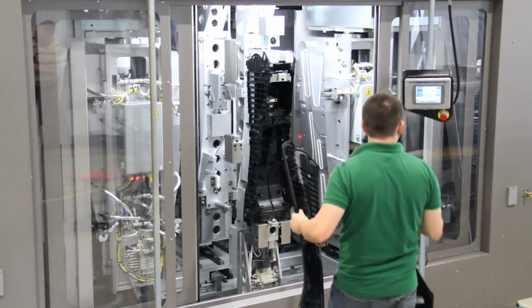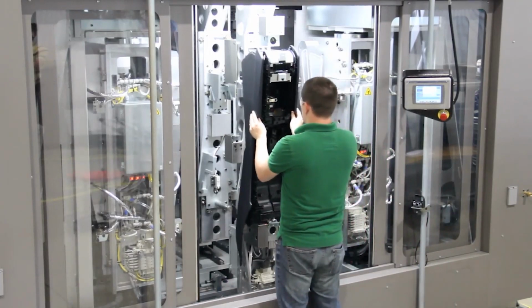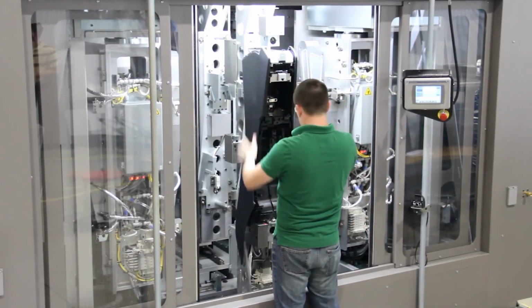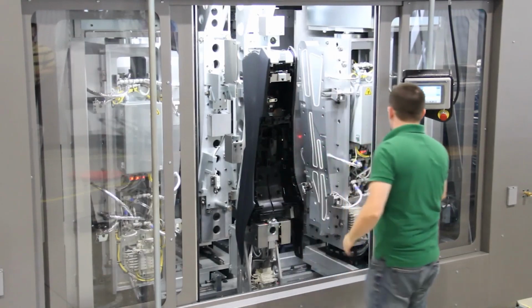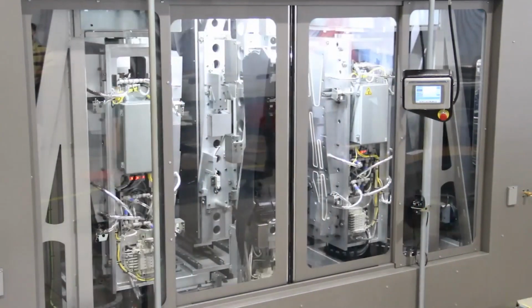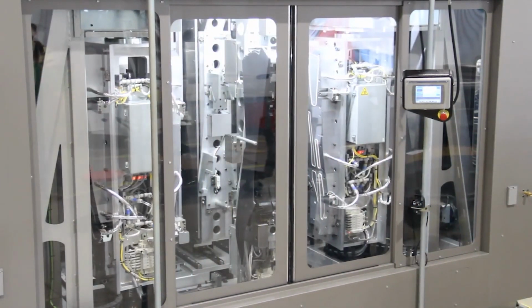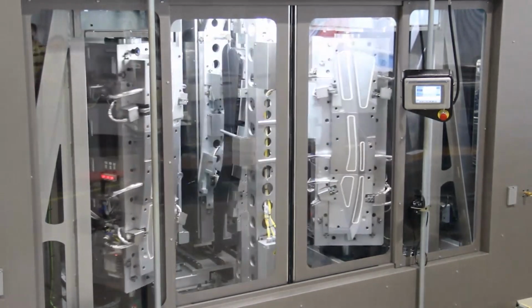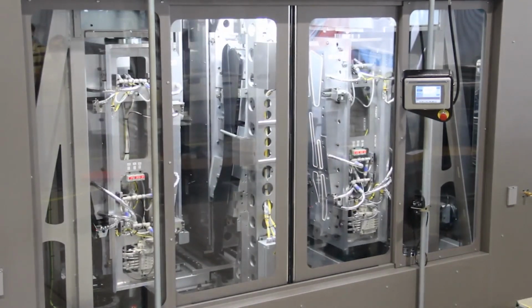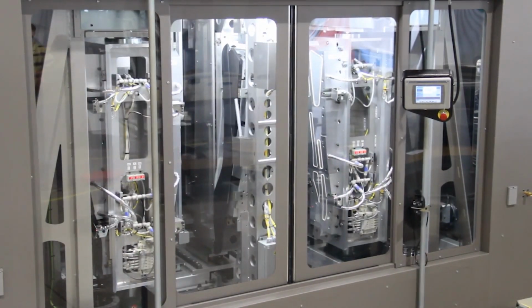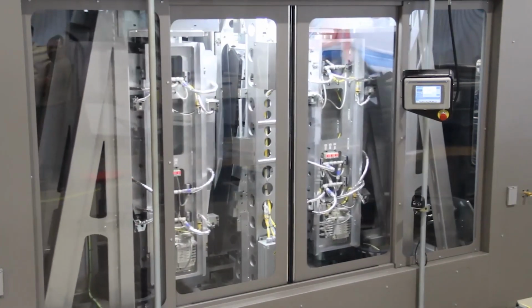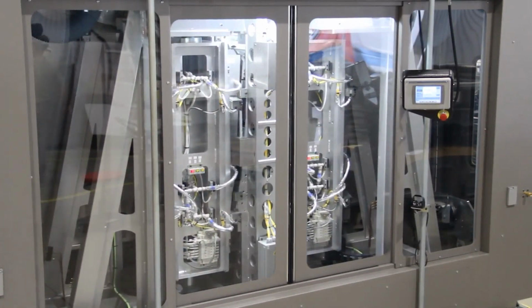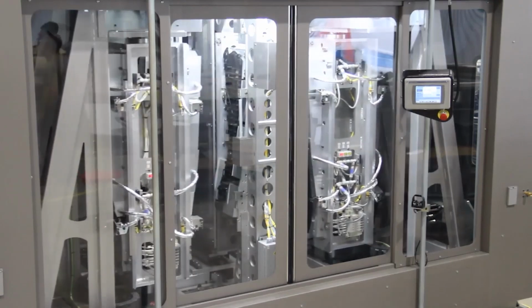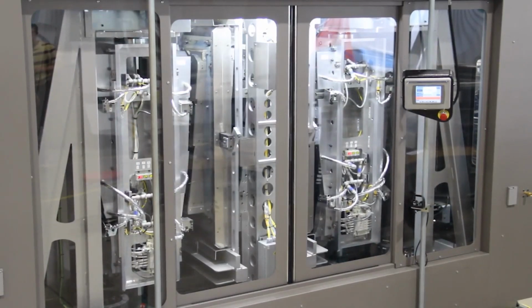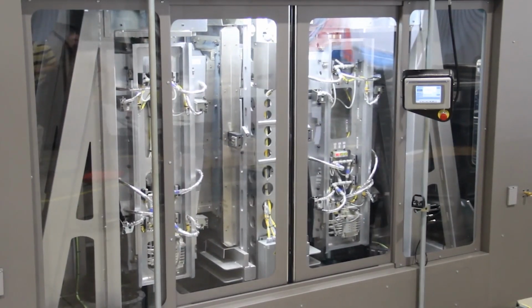And so it's a big part, and it's got lots of contour. It's decorative. People are going to see it. Here the operator is loading the sides, and this machine was actually capable of doing a tool change between two different variants. So the two side pieces are rotating because it recognized that it was switching part variants. And then they come in and grab those decorative trims off of the main center console. And then the heat plates come in. There's two of them. And we're going to do two hot plate welds at the exact same time.